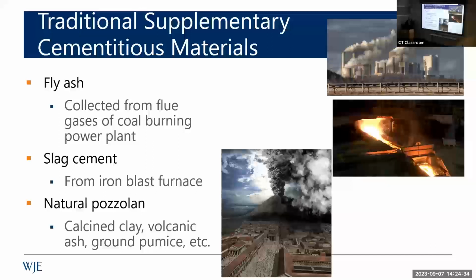Slag cement, same thing. Slag cement is made from iron blast furnace slag. Instead of taking that slag and running it into a pit and allowing it to air cool, you run it and quench it in water through a granulator, creating something that looks like sugar that you then grind up, and it's a fabulous cement on its own or with an alkali activator, such as Portland cement. How about blast furnaces? Are we building more blast furnaces in the US right now? Not so much. We're granulating about every source of slag cement that's economically viable to do so right now. So you're not going to see more of that. We're going to import more, but you're not going to see it being manufactured here.